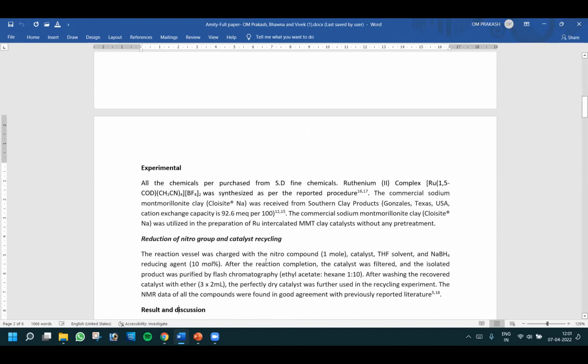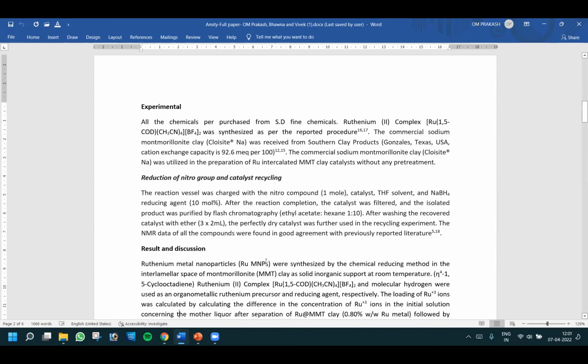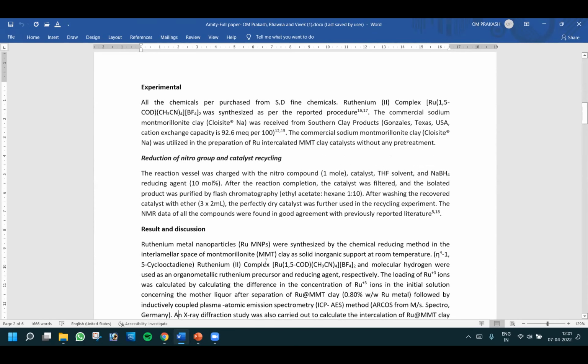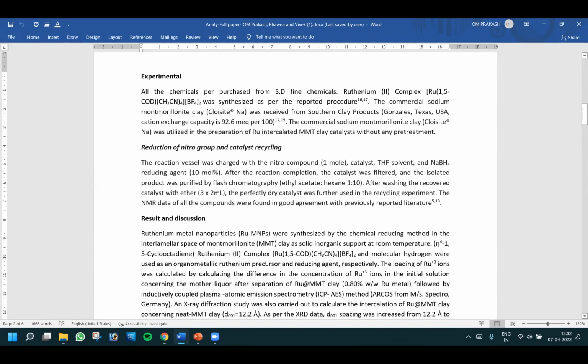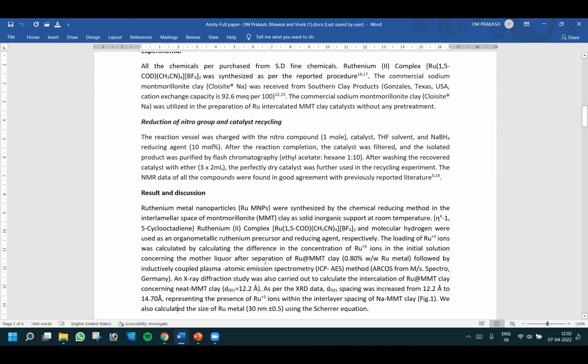This is the experimental part of my research paper, as shown, representing the reduction of nitro group and catalyst recycling. The vessels are charged with nitro compounds, 1 mol% catalyst, THF solvent, and sodium borohydride reducing agent. After reaction completion, the catalyst was filtered and isolated. Product was purified by flash chromatography. After washing, the recovered catalyst with ether was further used in recycling experiment. The NMR data of compounds were found to be in good agreement with previously reported literature.